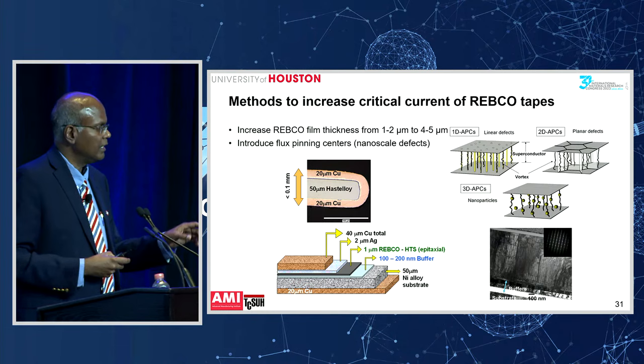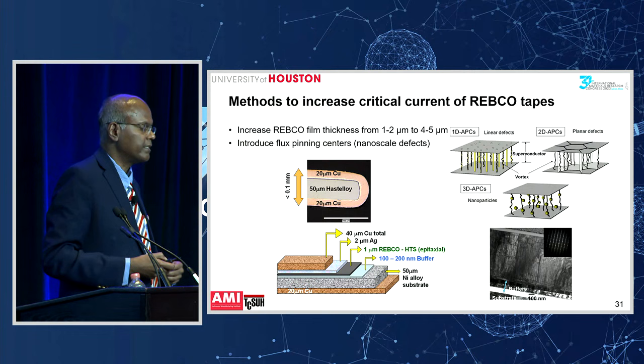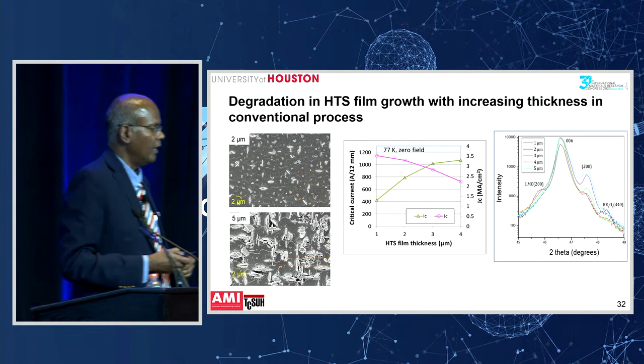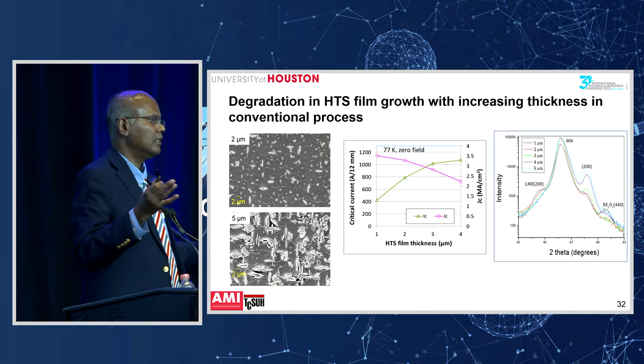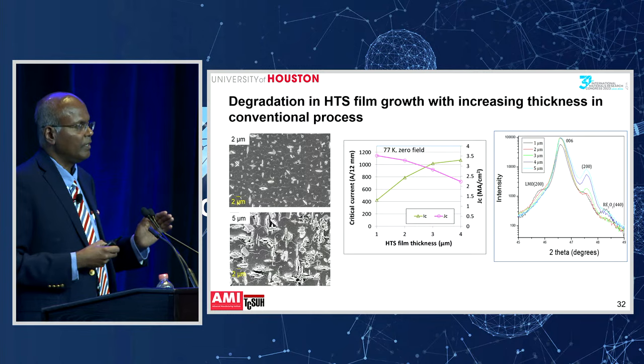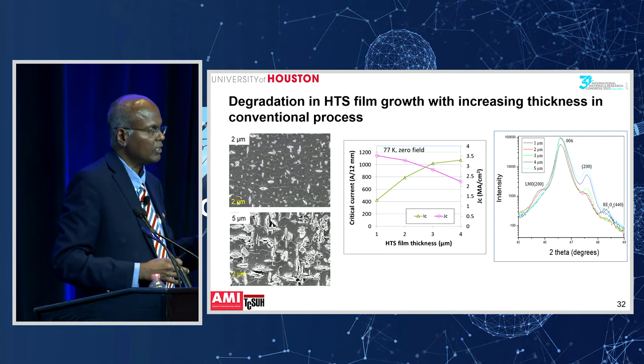The second thing is to introduce pinning centers. I already mentioned pinning centers. Can you make them more effective, right? So here's where the material science comes in. How do you make the current carrying capacity 10 times more? All right, so unfortunately, it doesn't easily work that you just make the films thicker and it carries more current. I'm showing the chart in the middle: if you increase the film thickness from 1 to 2 to 3 to 4 microns, the current is not increasing linearly, right? It's starting to plateau, it's starting to saturate.